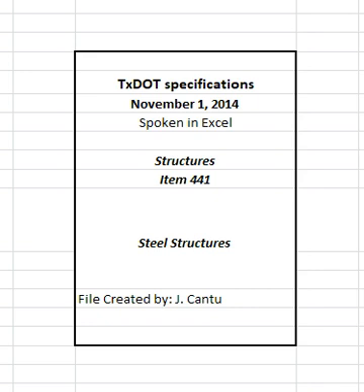Build the concrete bearing area up to the correct elevation once it has been placed below grade using mortar that meets Item 420, concrete substructures, and provide adequate curing. Use only mortar for build ups between 1/8 inches and 3/8 inches thick. Use galvanized steel shims or other approved shim materials in conjunction with mortar if the bearing area must be raised more than 3/8 inches.